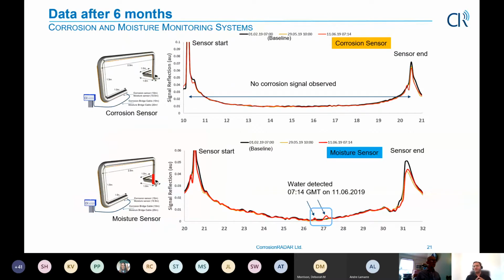Over a period of time, after 6 months, the top plot is showing the raw signal of the corrosion sensor. The black line is the baseline on day 1, and the red line is after 6 months, almost matching, no corrosion observed. But in the case of the moisture sensor at the bottom, you see the red lines. There are some very minor indications starting to happen that water is coming in. If you map it to the 3D model on the left-hand side, this is somewhere at the bottom of this pipe. And that's the power of this data, that you can map it to various locations.